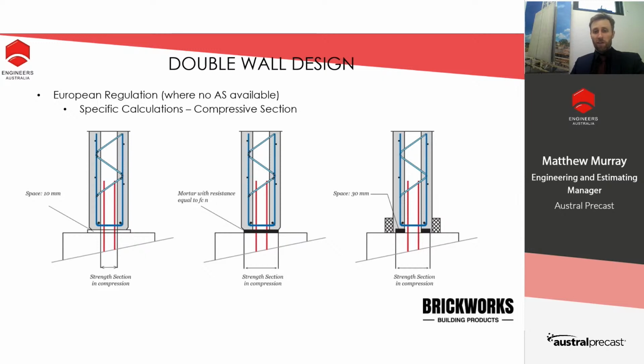And I think in light of recent engineering faults that have happened in Australia, this is our preferred option. So for that, we will typically use a nominal 30mm spacer at the base of the panel, and this will allow the concrete to get underneath the panel. So the picture on the right-hand side here shows the two spacers in black. There will be a pair of spacers 600mm in from either end of the panel. They might only be, say, 100mm in length each, and then the concrete of the core fill will be underneath the remaining section of the panel. So essentially, this gives us full continuity of concrete between the double wall and the panel, which is our preferred option and is a far more robust method of construction on site.